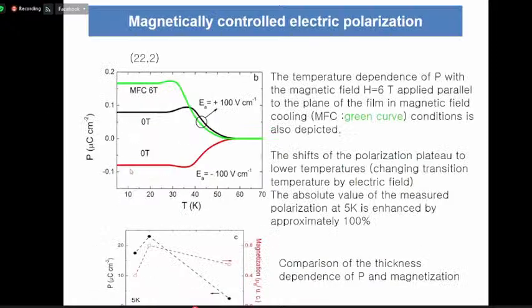Okay, this is the polarization result. We applied a magnetic field of around 6 Tesla, and then the electrical polarization changed. It's going up almost twice like this. Yeah, it's an electrical polarization, but it is interacting with the magnetic field.